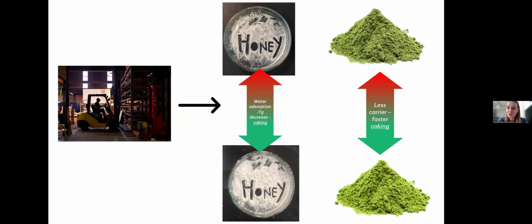One last thing that I would like to mention is the storage. It is a very important issue, especially for then handling the powder. So obviously, when the amount of the carrier is reduced, an additional challenge may arise during storage because powders with lower carrier content may be more prone to caking due to water absorption. Water is characterized by a very low glass transition temperature, minus 135 Celsius degrees. So if the powder absorbs the water, the overall glass transition temperature will decrease and we'll observe caking and problems with handling.